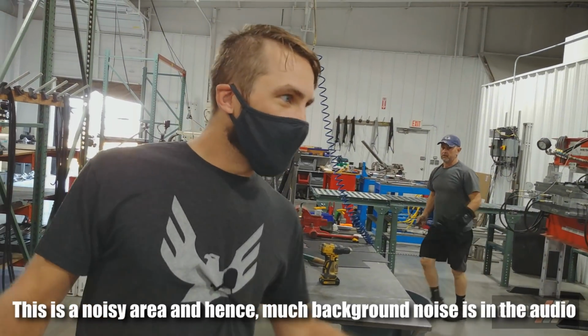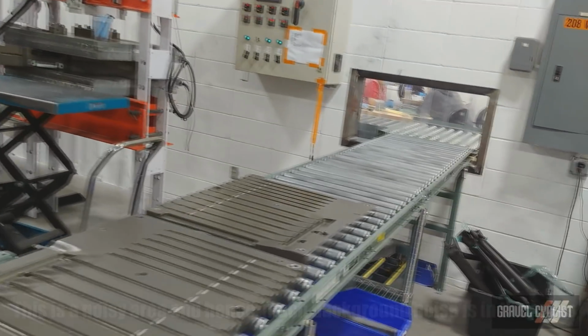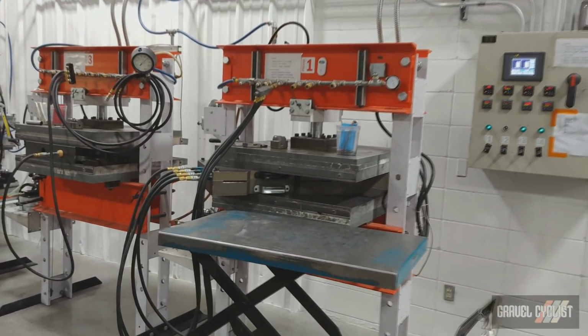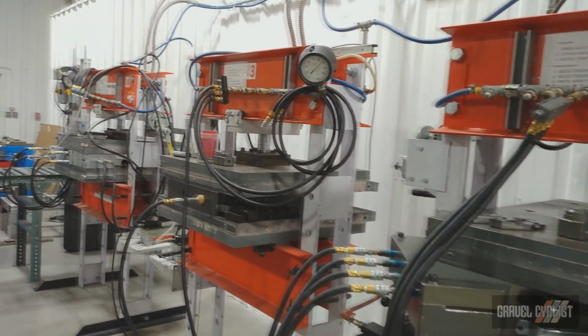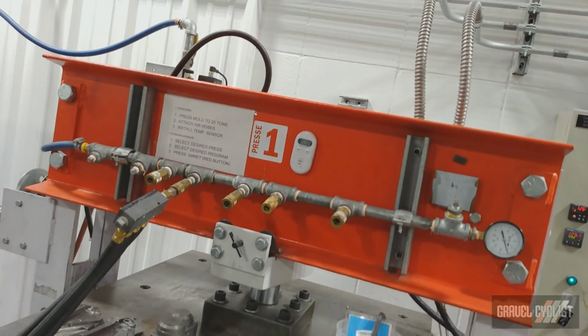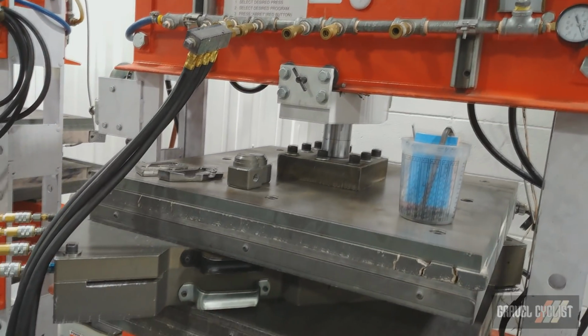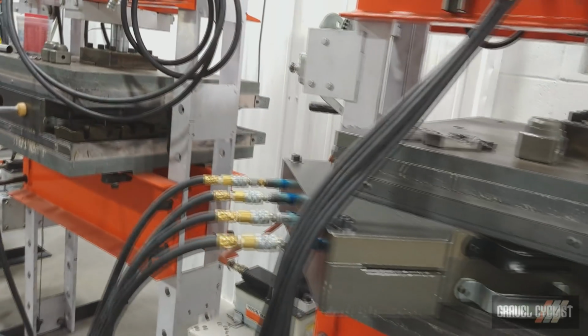All right, so once the tools are loaded, the tools come out here to where the carbon presses are. We have 3 presses. The presses use a trifecta recipe of physical pressure, 25 tons of it, air pressure, 125 psi of it, and temperature, about 230 degrees Fahrenheit of it. And that will essentially cook, as we call it, for about an hour, and then the pressure will blow off. The tool is ready to come off of the press, and it comes over here to this table.